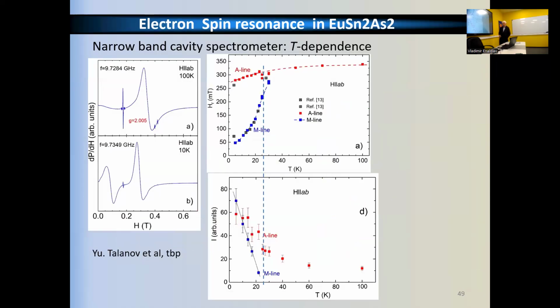Being encouraged with this success, we repeated the measurements with a more sensitive technique. It's a cavity spectrometer with a fixed resonance frequency but varying temperature. And again, we see the splitting of the resonance line, and we explore this as a function of temperature, not magnetic field, but temperature. And again, everything develops as in a textbook. The black rectangles are reproduced from Igor's measurements, and blue and red are the new measurements.